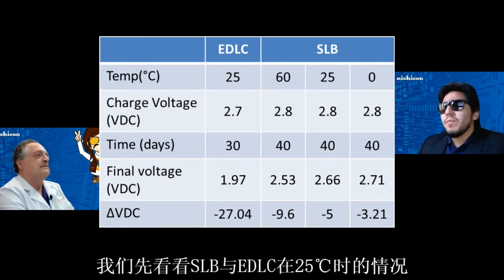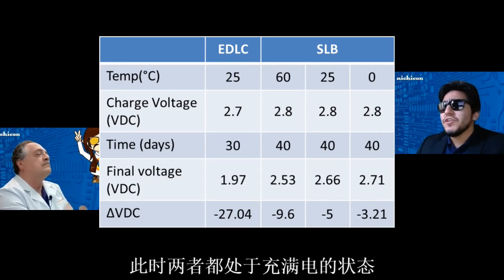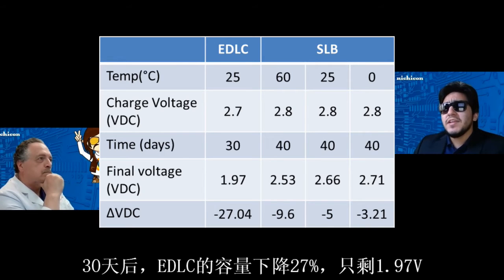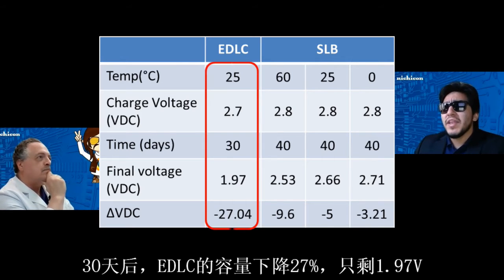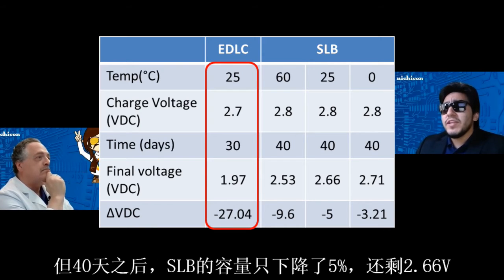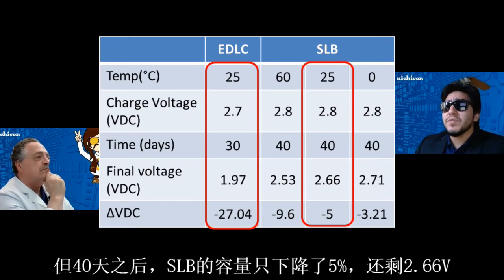We are going to look primarily at the 25 degrees C for both. You can see the parts are fully charged. After 30 days, the EDLC voltage had dropped 27%, down to 1.97 volts DC. But after 40 days, the SLB had dropped only 5%, down to 2.66 volts.